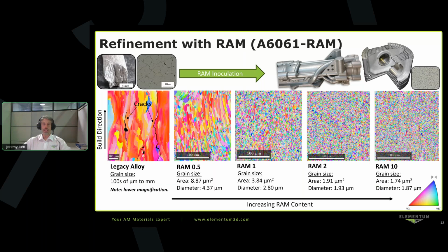Here's an example looking at a 6061 based aluminum alloy. On the left is the standard wrought 6061 composition. If you try and print that with laser powder bed fusion, you can see in this EBSD image the columnar type structure with the growth direction going upwards. So each layer solidifies on the previous layer below on those same crystals, and then builds those crystals upward until they're millimeter scale macroscopic crystals, and leads to cracking between those. The colors that you see there are also very similar, which shows that those crystals tend to be oriented in similar orientations, which is also not great for having properties that are equal in all directions, and also tends to lead to more problems with the cracking.